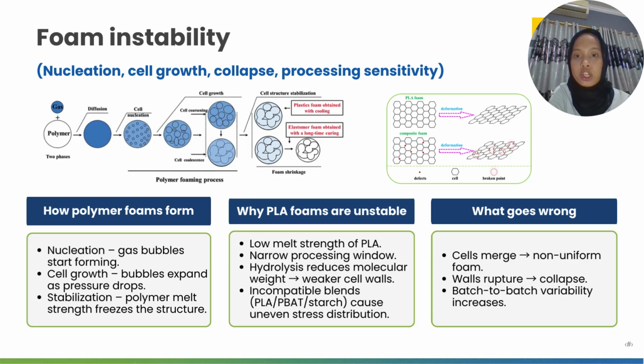Next is foam instability: nucleation, cell growth, collapse, and processing sensitivity. How do polymer foams form? First is nucleation, where gas bubbles start forming. Then cell growth, where bubbles expand as pressure drops. Then stabilization, where the polymer melt strengthens and freezes the structure. And why are PLA foams unstable? Because of the low melt strength of PLA, a narrow processing window, hydrolysis reducing the molecular weight, weaker cell walls, and incompatible blends causing uneven stress distribution. And it goes wrong: cells merge, leading to non-uniform foam, like in these pictures, walls rupture or collapse, and batch-to-batch variability increases.